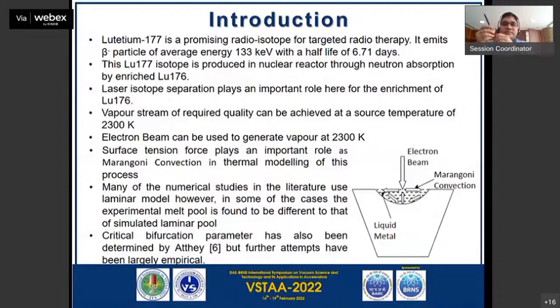So how is this isotope produced? It is produced by neutron absorption in a reactor of lutetium-176. Lutetium-176 is put in a reactor and bombarded with neutrons, which converts it into lutetium-177. Now, to get lutetium-176, we have to enrich the natural lutetium, from a natural percentage of 2.5% to more than 65 or 70%. We will do this through the process of laser isotope separation.